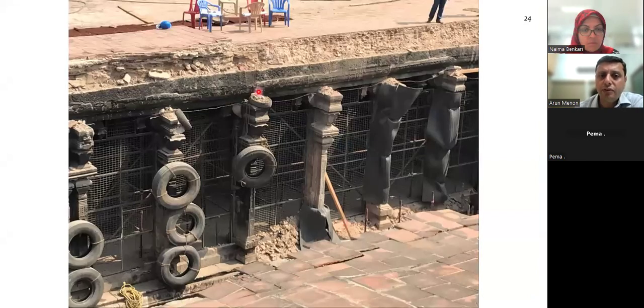Another important step that was taken was, since the roof was contiguous between the 1,000-pillared mandapam and the one that was affected by fire, at the roof level, a cut was made with a diamond drill bit. A cut was completely made so that if and when portions of the fire-affected structure were being dismantled, it does not cause vibrations and it does not pass on movements to the other structure. So what you see here is actually a cut made using mechanical cutters.